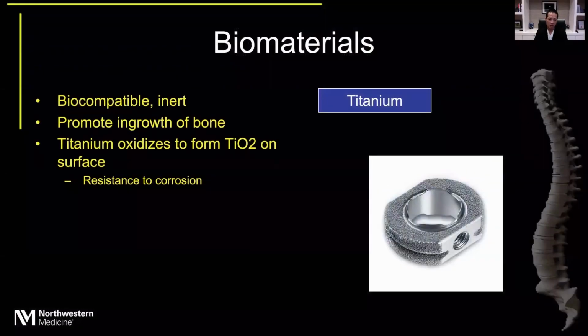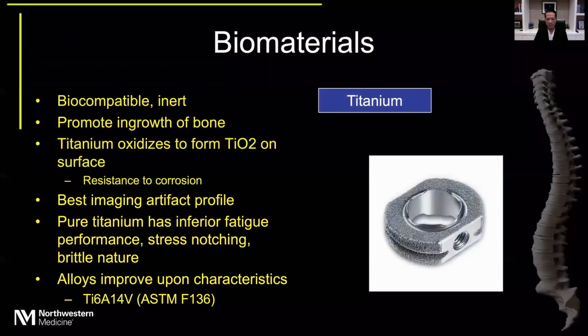Titanium is a biocompatible and inert material that promotes the ingrowth of bone, and does by far have the best imaging artifact profile when it is compared to all different kinds of metals. If one were to use pure titanium, there are inferior biomechanical properties such as fatigue performance, stress notching, and brittleness. When we use it in vivo, alloys are used which improve upon these characteristics.